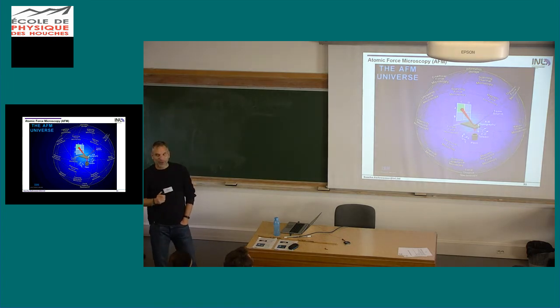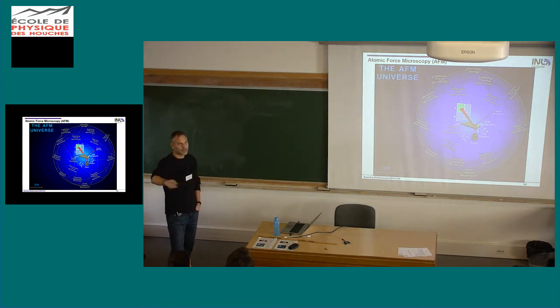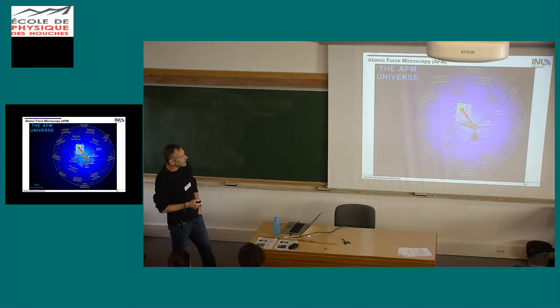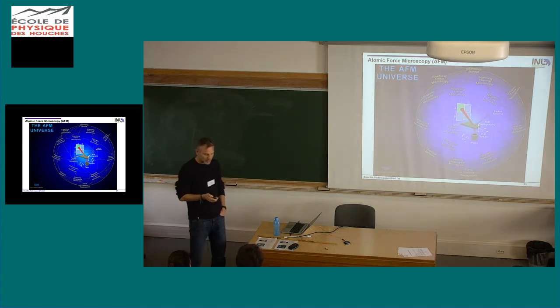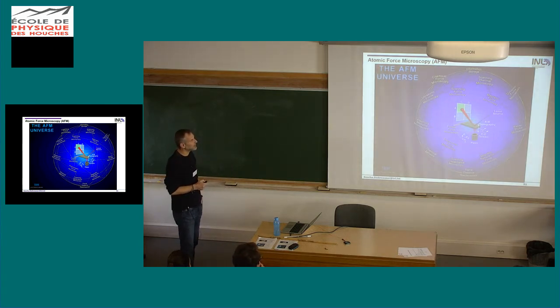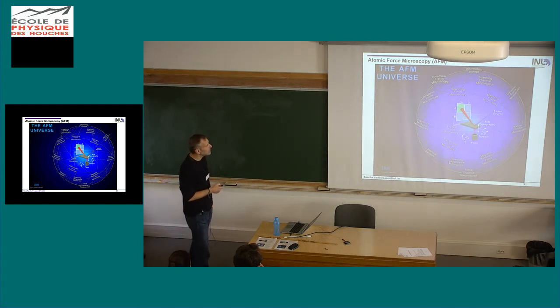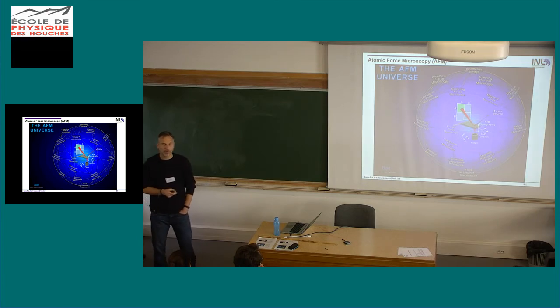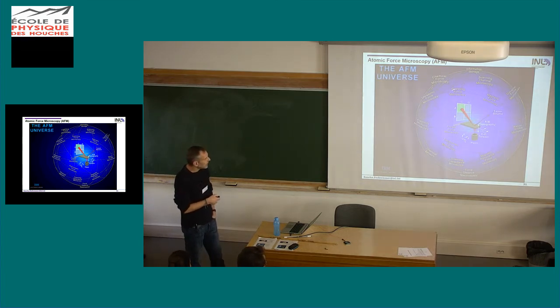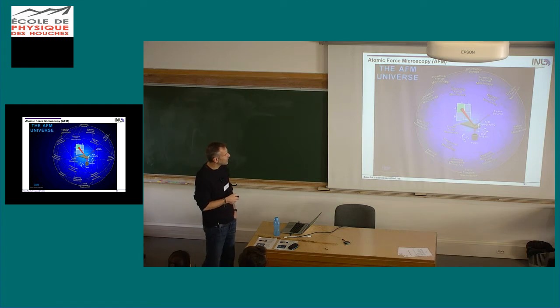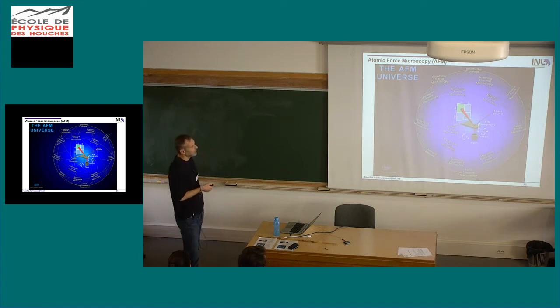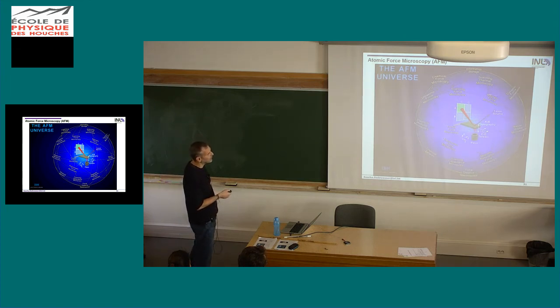So one of the powerful things is, so far we only saw the surface structure, the morphology, topography. Of course, you can go down to the atomic scale with these methods as well, but that's quite challenging. For PV materials, what's much more interesting and common is to combine atomic force microscopy with other methods. The simple one is scanning force microscopy or atomic force microscopy. But if you use a magnetic tip or a magnetic sample, you can actually do magnetic force microscopy. So you look at magnetic forces.